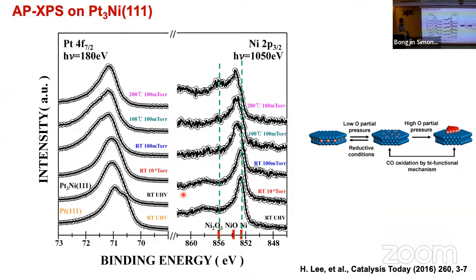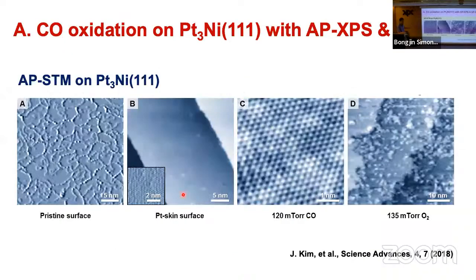And this right-hand side is the picture that reflects this situation. When you prepare very clean platinum alloys, you will see this platinum skin on the surface, which shows a very clean metallic state. But once you start to put the oxygen in, you start to have the oxide of the nickel being pulled to the surface, forming this oxide. And this is exactly what we are seeing here. So I presented these pictures to them. And then they wanted to compare with this situation.